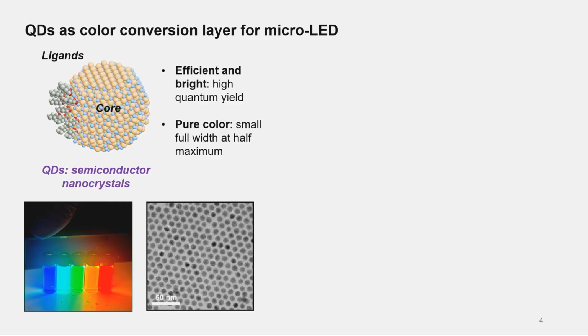The quantum dot is efficient and bright, which means the quantum yield is really high. You can almost reach 100% for many different compositions, and you have very pure color. The full width at half maximum is really small compared to many organic fluorophores. One thing I want to stress is that what makes quantum dots unique among nanoparticles is that you have a specific interface between the ligand and the core. So in most cases, when you modify the surface, you really don't change the optical properties of the core. This gives you a lot of flexibility to make the particle compatible with the surrounding medium if you want to use it in other applications.